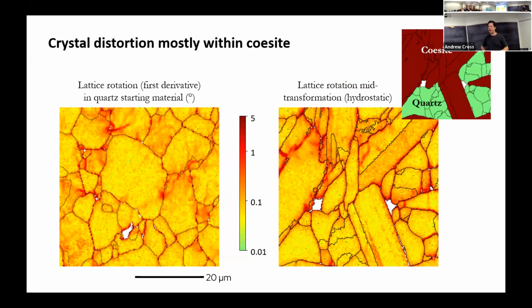Right, so here's that same map on the left. This is our quartz starting material. So we've got some internal deformation of the quartz starting material. It's not perfectly undeformed. We've got a few subgrain walls and defects in there, but not an awful lot. Now, if we look at the same type of map, one of these misorientation maps for our hydrostatic case, so